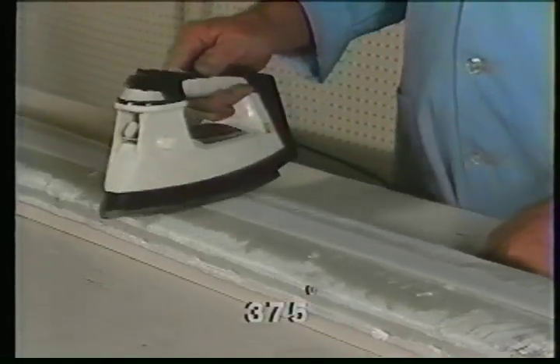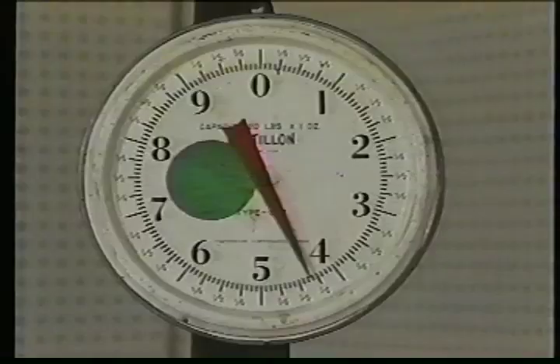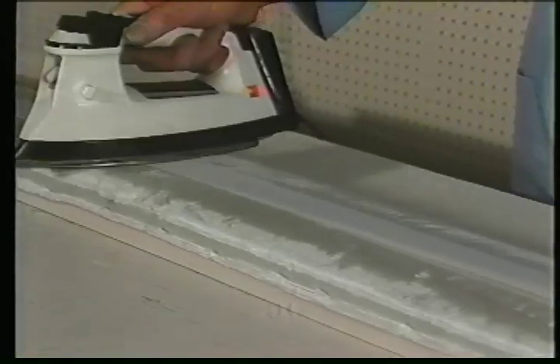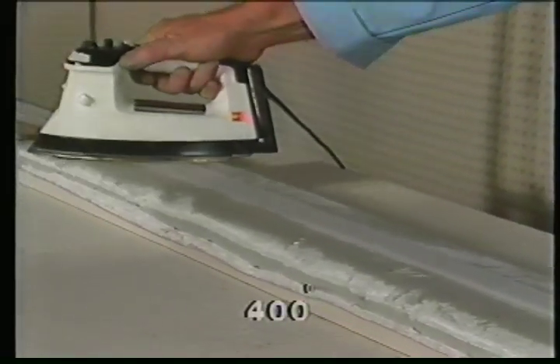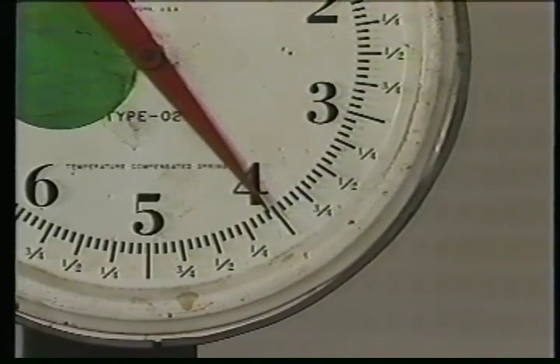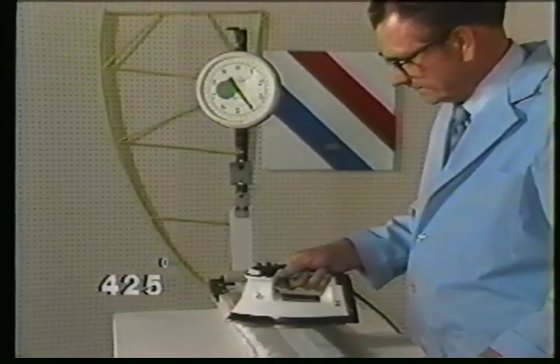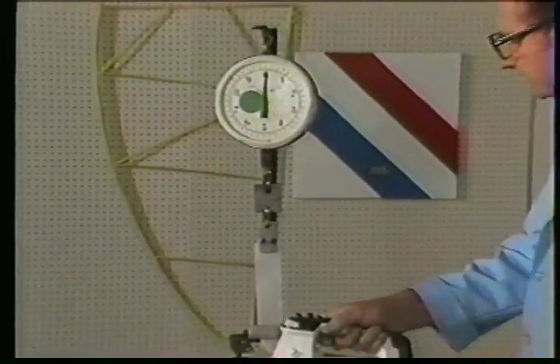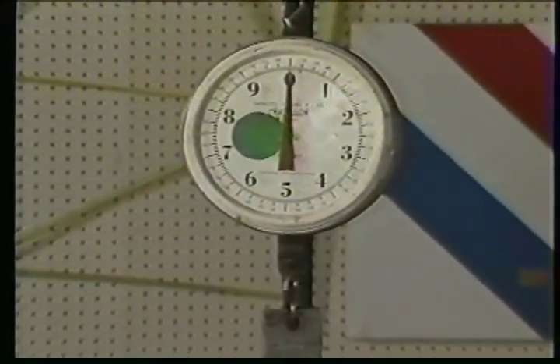At 375 degrees, the tension is starting to release and now reads only 4 pounds 6 ounces. At 400 degrees, the tension has dropped to 4 pounds 1 ounce. And at 425 degrees, as expected, the filaments have weakened as they start to melt, and the fabric has separated.